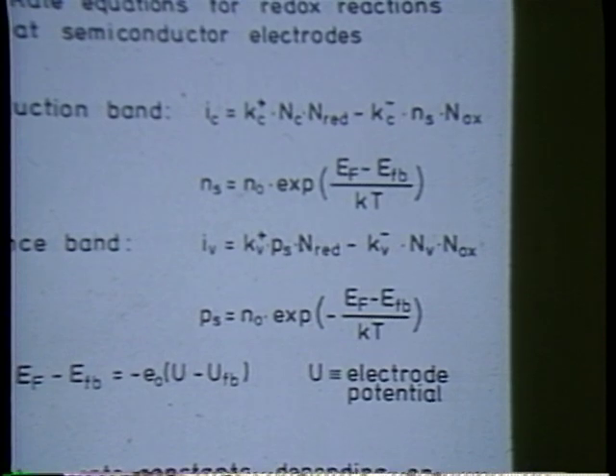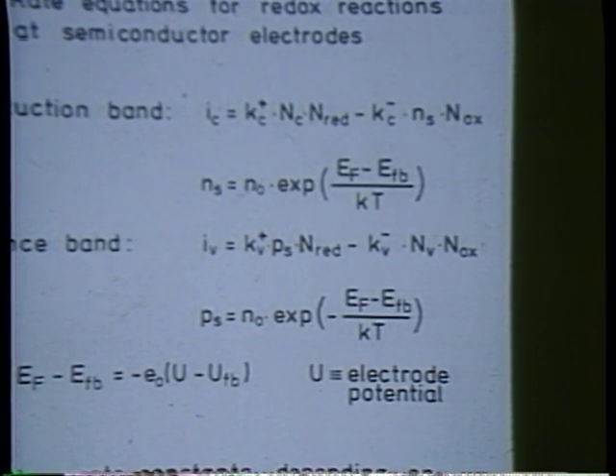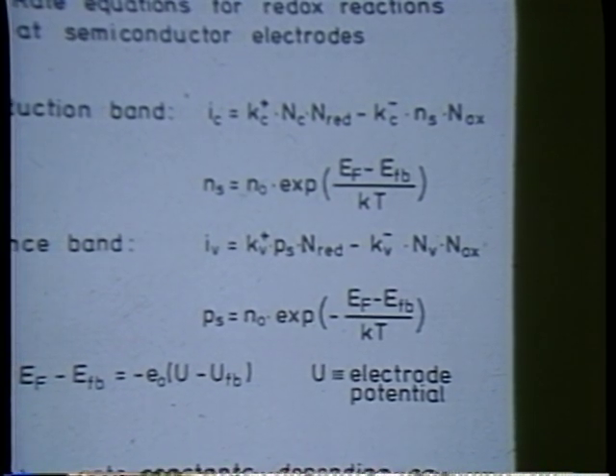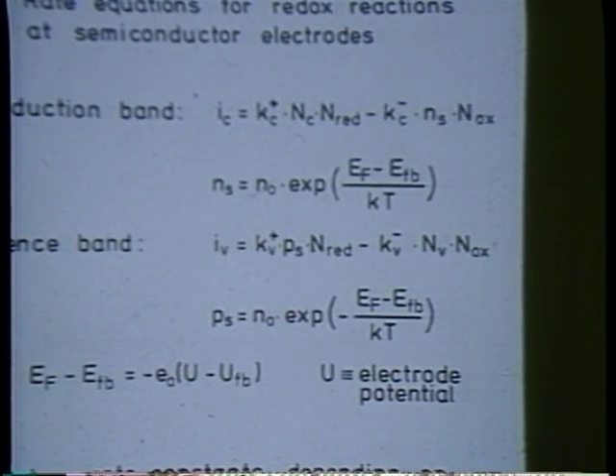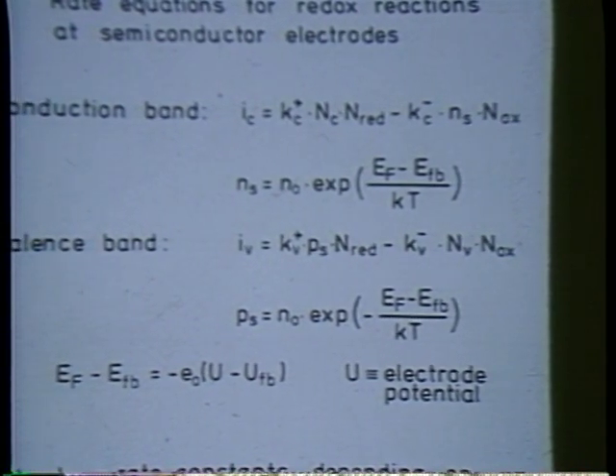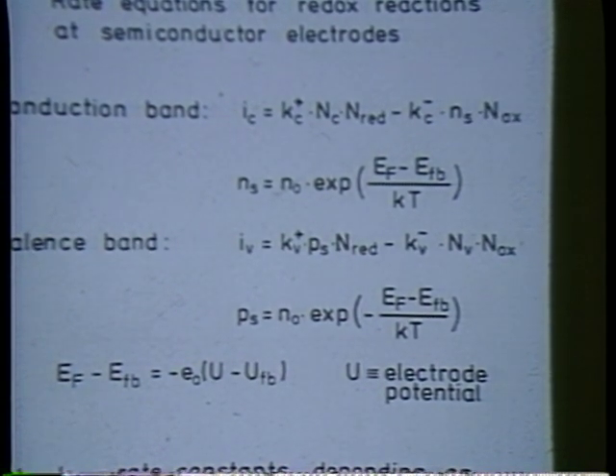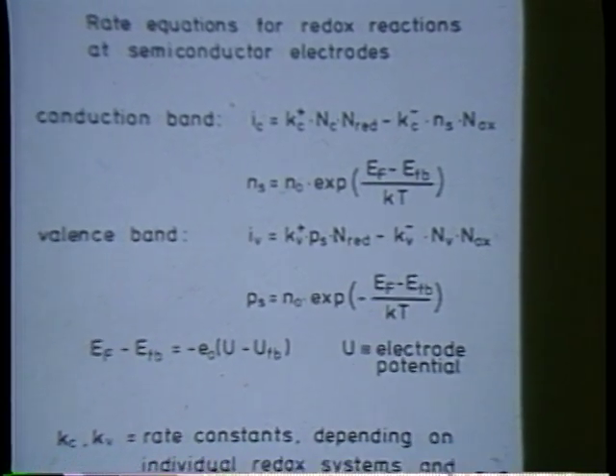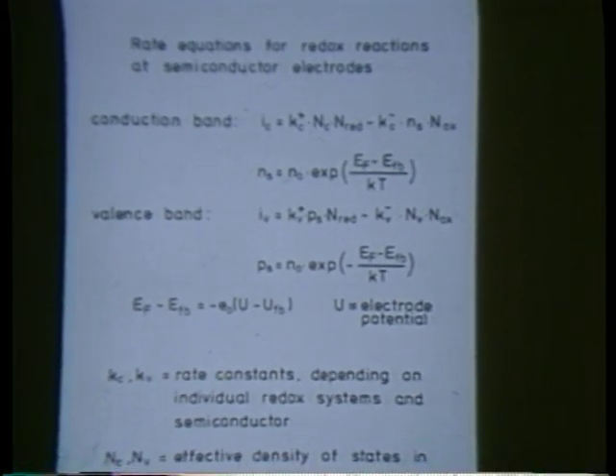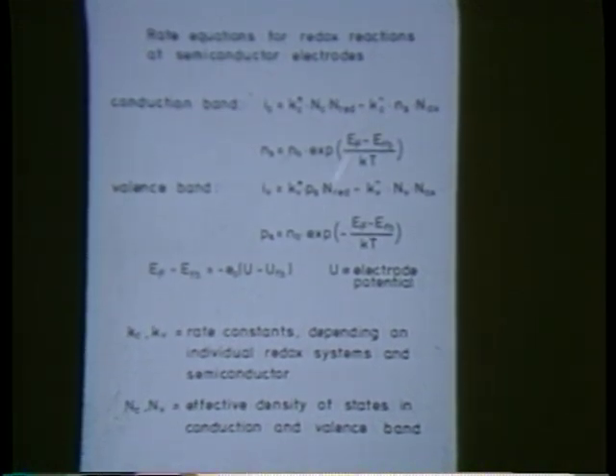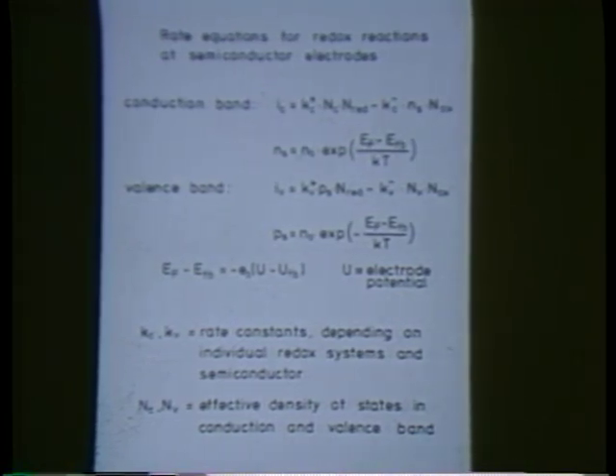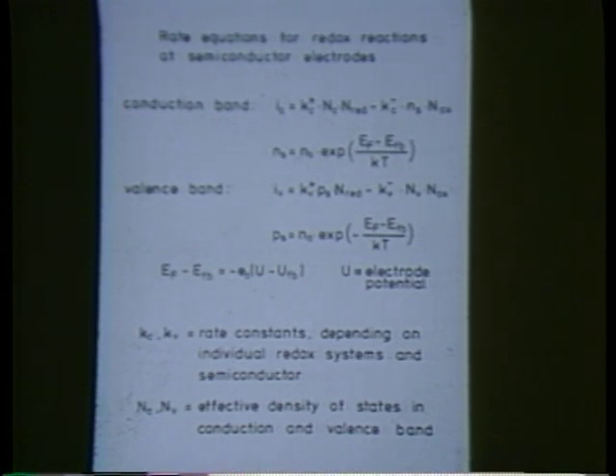So you see, the control of the reaction rate in the case of a semiconductor with a bias applied does not occur by the evaluation of the activation barrier for charge transfer. It is the concentration of the reacting electronic species. So it is, in thermodynamic terms, the entropy factor which is changed by the applied bias, not the energy factor.